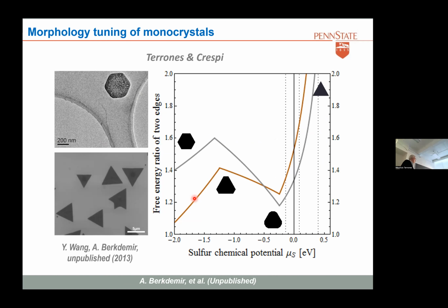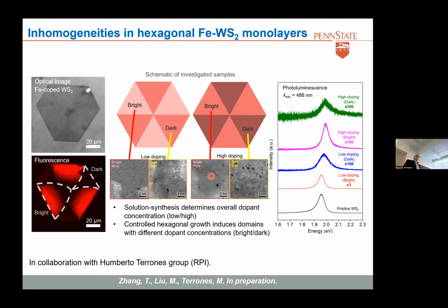and how these dopants affect the growth, that's going to your question, is that you can have different shapes, and that depends on the sulfur. One of the things might be the sulfur chemical potential. So you put lots of sulfur in your reaction, you tend to create these triangular lattices. If you put less sulfur, you get this hexagonal lattice. But there are other parameters besides when you put another element there. And this is something that we have seen with the iron and the tungsten.